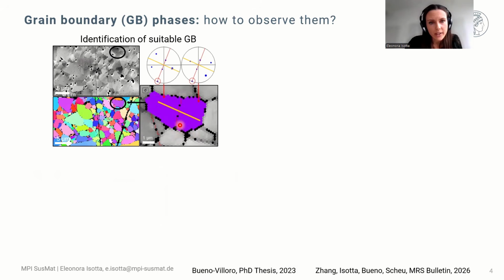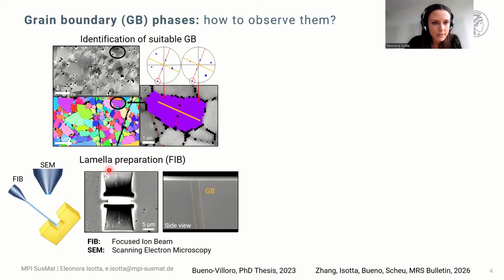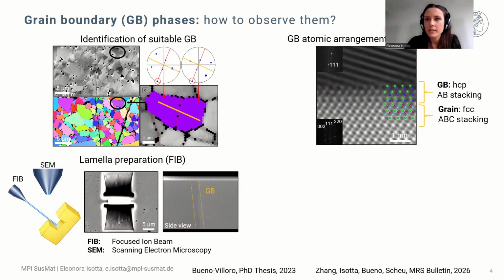Once the boundary is identified, we proceed with preparing a lamella for TEM observations using focused ion beam. This technique allows us to carve a shape into our sample, and a lamella can be extracted and thinned down until it reaches electron transparency. After this, the TEM observation can be carried out with STEM or high resolution TEM mode, which allows achieving very high resolution if the lamella is properly prepared. This allows us to detect and infer the atomic arrangement that develops at the boundary.